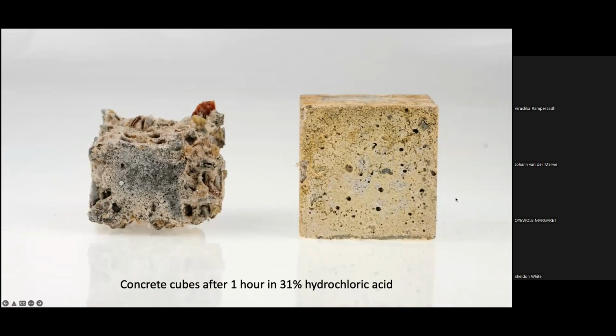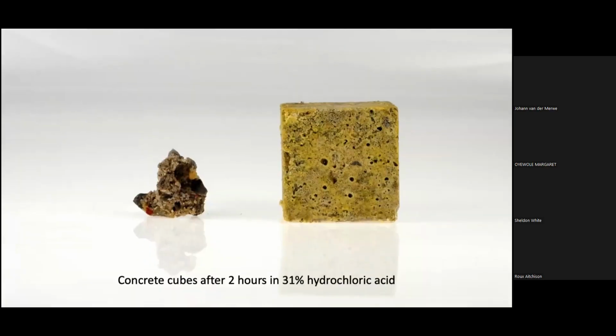These cubes were made out of the same concrete, out of the same wheelbarrow. The only difference is that the one on the right was treated with a spray applied colloidal silica. And we dunked them in acid. This was done while I was at the university. Put them in a 31% hydrochloric acid. After 1 hour, you can see the difference. And that's just because the pore structure is being closed. You don't have that surface area that's being attacked. After 2 hours, you can obviously see the difference there.